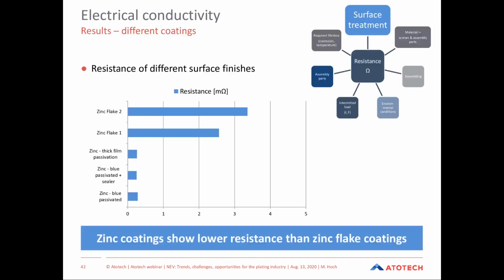The resistance, for example, is determined by numerous different influences and parameters, like the material of the screws and the assembly parts, the assembling step itself, or environmental conditions. We in our industry can only influence the surface treatment itself. And here we found that galvanic zinc coatings show lower resistance than zinc flake coatings.